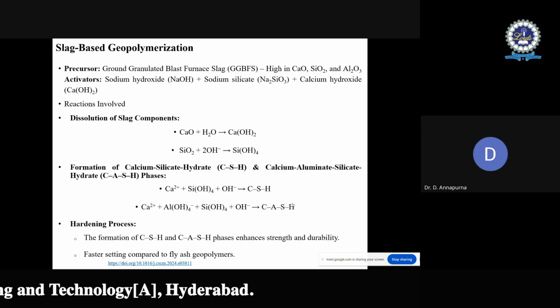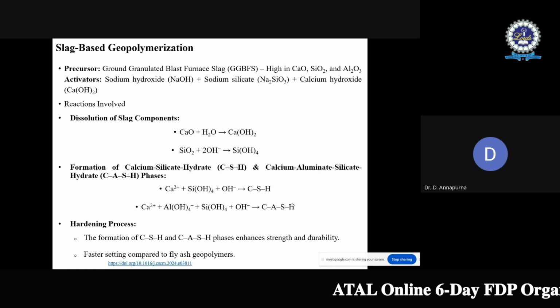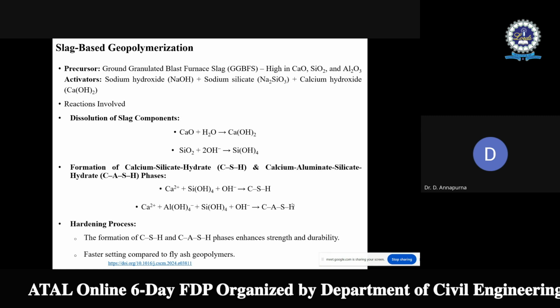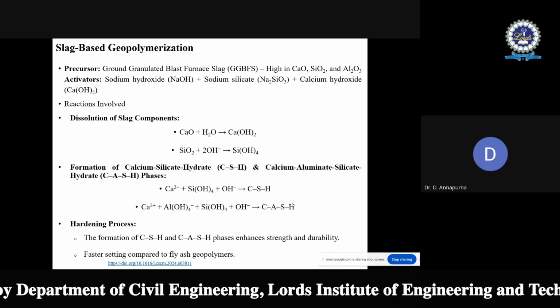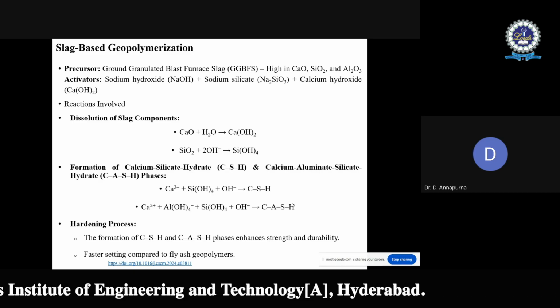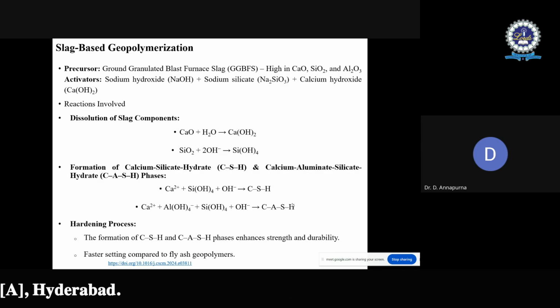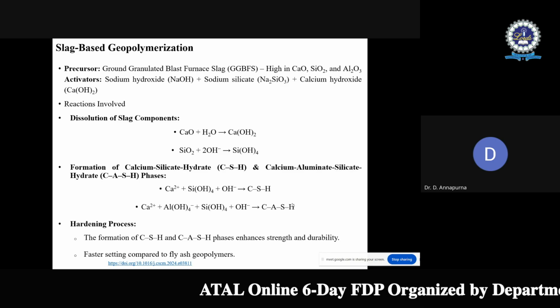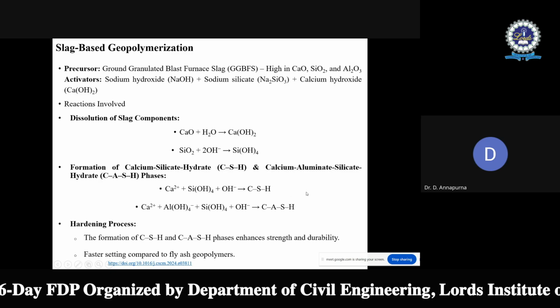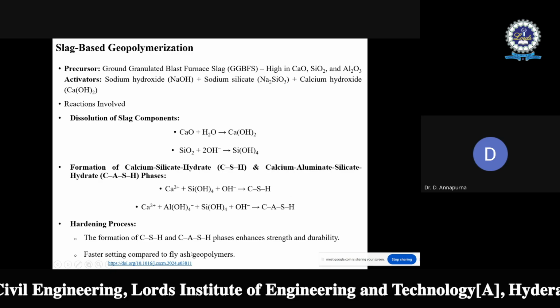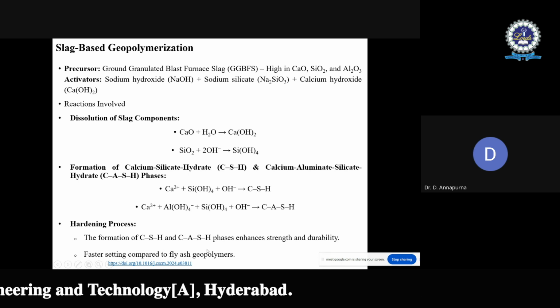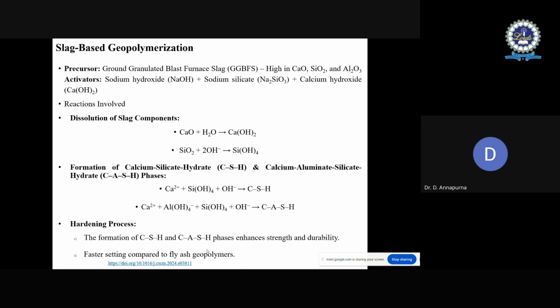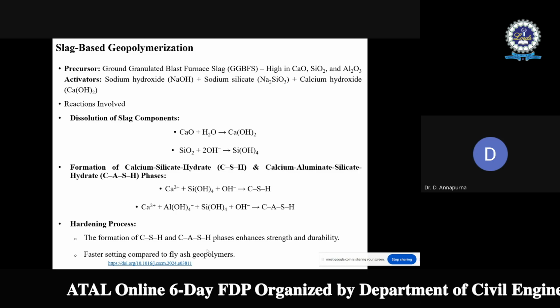Heat curing is maintained at 60 to 80 degrees for one day. So the geopolymerization process occurred and they got NASH. But in practical considerations, preparing concrete using heat curing conditions every time is not possible. That is the reason a calcium oxide rich material like GGBS was introduced as an admixture to fly ash based geopolymer concrete. Thereby it gives calcium aluminate silicate hydrate gel. The setting action of this geopolymerization process is very fast compared with fly ash geopolymers. When only fly ash based geopolymers were prepared, it took more than 2 days to set.